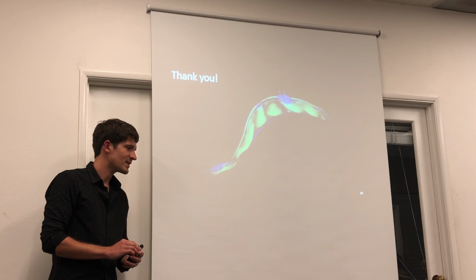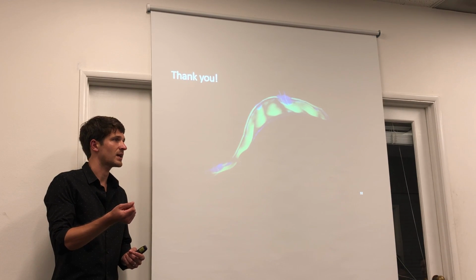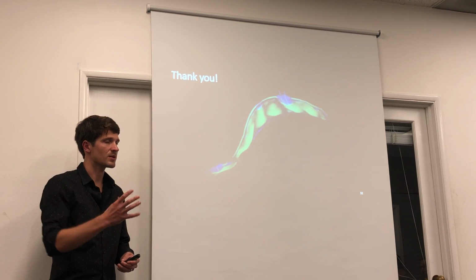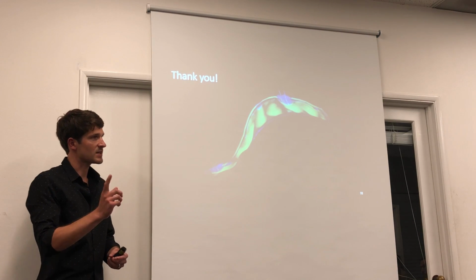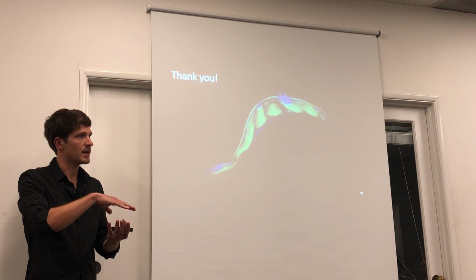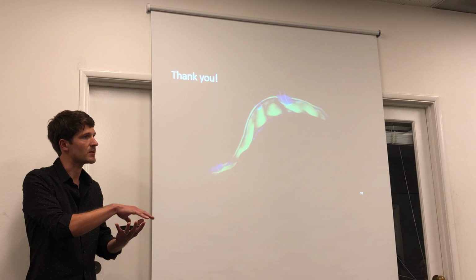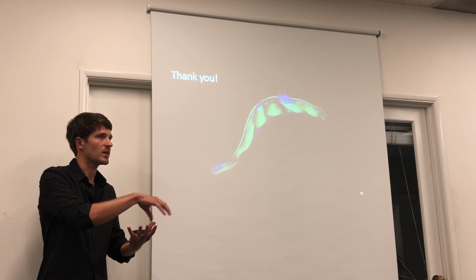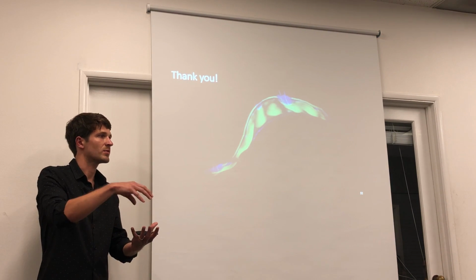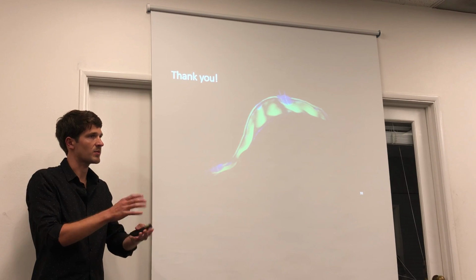No, it's a layer by layer process. Say you have a liquid rubber that will cure under ultraviolet light, so it goes from a liquid to a rubber under ultraviolet light. They'll take a spinning disc, pour the rubber on it, and spin it really fast to get a thin, uniform layer of it, and then they'll pattern on their electrodes. They can use something like what you would use for microfabrication, like for making chips. You can apply carbon nanotubes through masks to delineate where your actuators are. Then they spin another layer on top of that, cure that under a black light, and then electrodes. They just keep repeating that process, and then they have a stamp that will cut out each of their stacks, and then they assemble those into actuators.